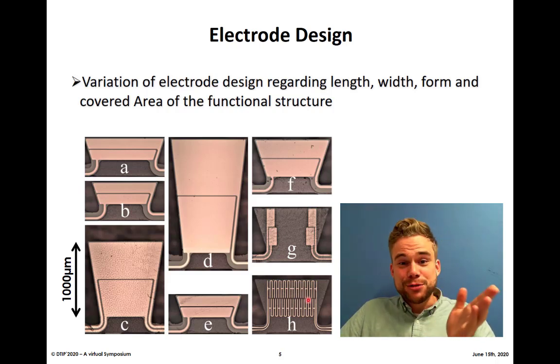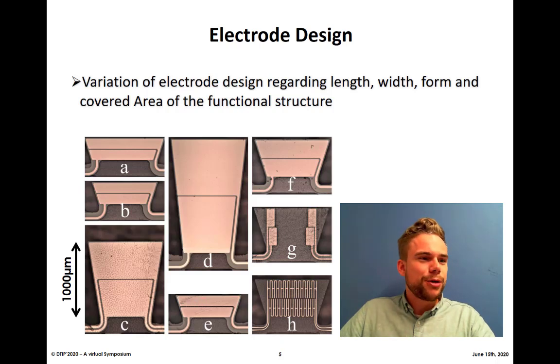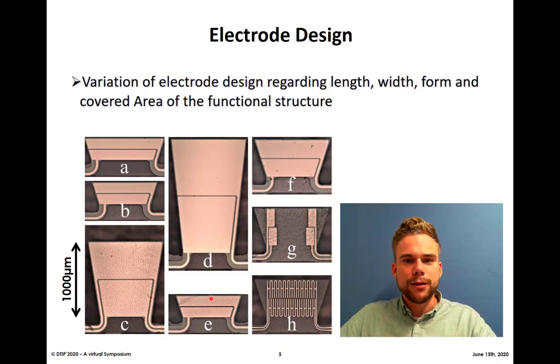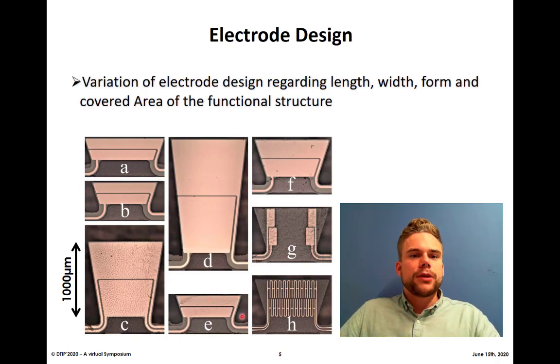Okay, and you might ask, what is the difference between B and E? Some of us with great eyes see that there is a small black line between B and E. The rest is kept the same. And this small line between the top electrodes of E, the proximal and the distal electrodes, is a small notch that we put inside the aluminum nitride to decrease the total stiffness of the structure. The hope, or the aim, was that we decrease the stiffness of the total structure by applying this small notch between the top electrodes. Okay, so this is about the different electrode designs we tested for the flapper.